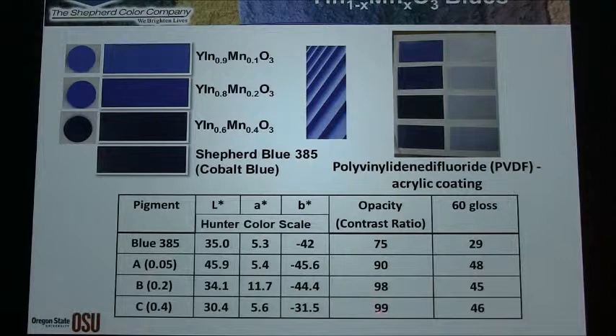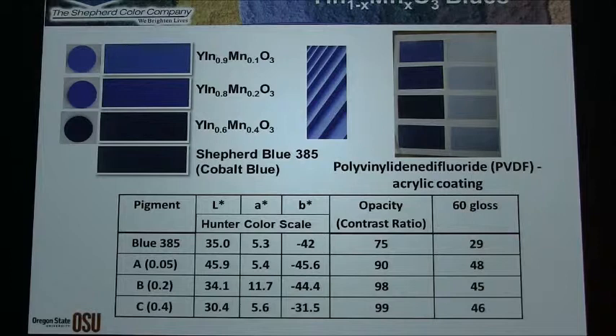This is a 60 degree angle gloss. You can see that our painting produces much more glossy prints than the one used by the cobalt blue. So I'm comparing the blue which is commercially available today versus our blues actually.